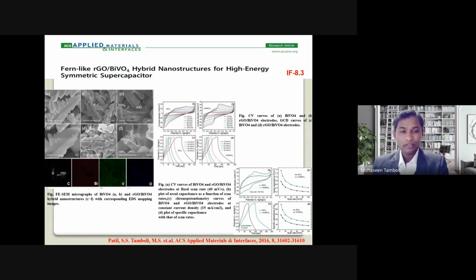When we go for a higher loading of RGO, some small sheets are observed in the FESEM, but you can clearly see the fern-like structure showing here, which means the BiVO4. When we go for the elemental mapping, it shows all the elements are present here, like bismuth, vanadium, oxygen, and carbon.